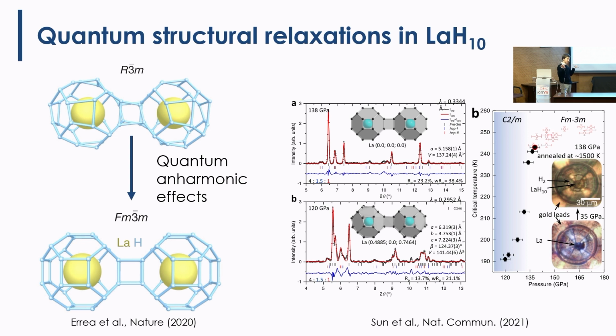If you remove the hydrogens here and just do a DFT calculation of the electronic density of the lanthanum scaffold, you see a strong electron localization where the hydrogens are later absorbed. So maybe this is the chemistry behind the formation of these high electron-phonon coupling materials. What we know is that what you need is that this kind of hydrogen network is covalently bonded between each other somehow. This is what you need to have a large electron-phonon coupling. In most cases, this is what you see. And this is the basis that we use to predict the critical temperature very fast with a big error, but it's useful. So this is where the chemical intuition goes.